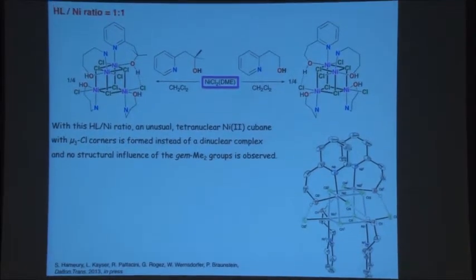If I now first move to the 1-to-1 ratio chemistry, we start again from the same precursor, and I take my C2 spacer ligand with no methyl over the 2-methyl. In both cases, we obtained cubane type structures, with nickel 4 stoichiometry, 4 chlorides completing the octahedron, the cube here. And our ligand here is chelating the nickel center, and again you see intramolecular hydrogen bonding interactions between the alcohol and the chloride ligands. The same applies to both structures. And this is rather rare.